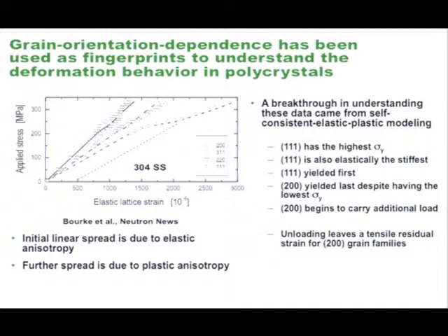If you don't have a load frame, you can do similar studies ex situ. You load it up, come down, and study the residual intergranular strains for different reflections, and you can get similar answers. It's not quite the same, but you can get similar answers.